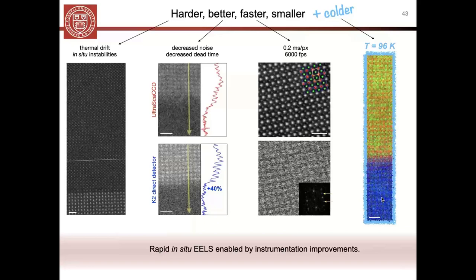But it's not just so straightforward as dose. There's also things to consider like dose rate and also the area. And so even with the very high probe currents, as long as you can run really fast, some materials are more sensitive to the total dose and some more to the dose rate. And so, for instance, if you can run very, very fast with a high probe current, that might be okay in certain cases. And as well, you can start to explore options like custom scans or some of the sort of aloof or leapfrog EELS techniques that other groups do particularly.